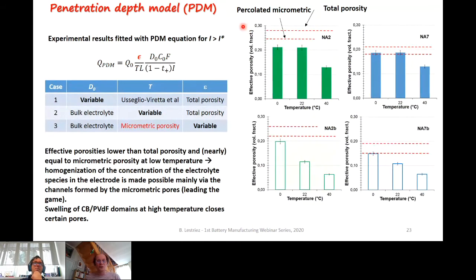So this suggested us to play with the model in a last way, where we have considered as diffusion coefficient that for the bulk electrolyte, and the tortuosity factor as being equal to that of the micrometric porosity, because from all what we've seen before, this is what is playing the game. And then we have used the porosity as the variable. So the results are shown here for the 4 electrodes, again as a function of the temperature, and they are compared to the total porosity, the upper line, and the percolated micrometric porosity, the lower line.